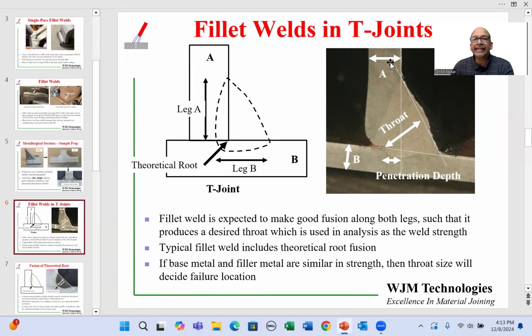A has a certain width, B has a certain width over here, and we can see the contrast of the weld. I'm tracing the arrow tip on the weld itself, and you can see that the weld is pretty large. We can also see that the shortest point of connection from the inner edge of the weld to the outer edge, which is the throat of the weld, is shown by this arrow segment over here.